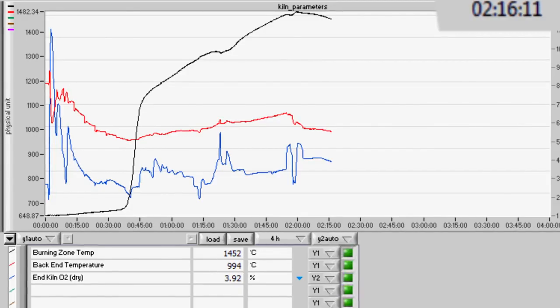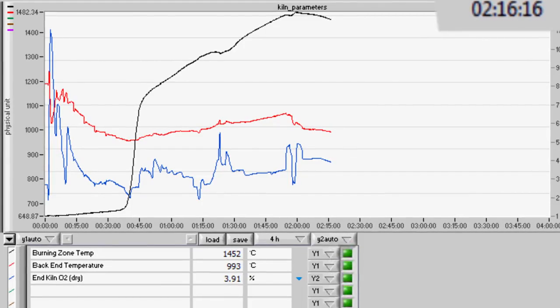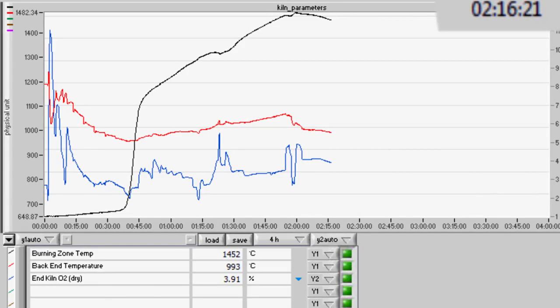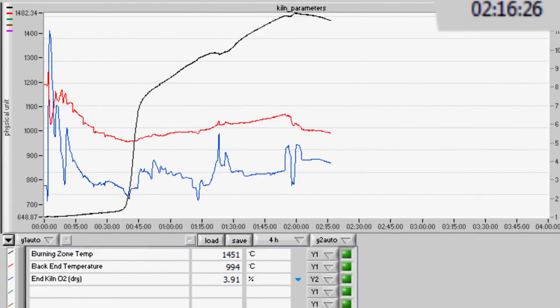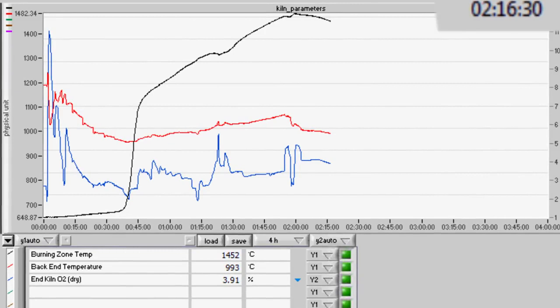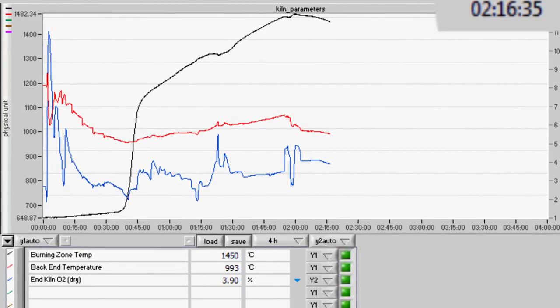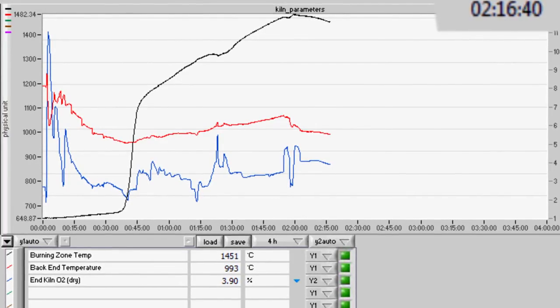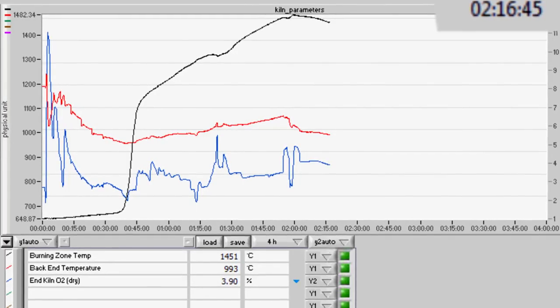Two hours 15, looking at the graphs starting from the beginning, that is, when the material was first fed into the preheater. The black line, the BZT, is starting to go down slightly. The red line, back-end temperature, stabilizing at around 1000 degrees Celsius. O2 kiln inlet a bit too high at 4%. The rule is keep your O2 as low as possible, making sure you do not generate CO, not even traces of CO.